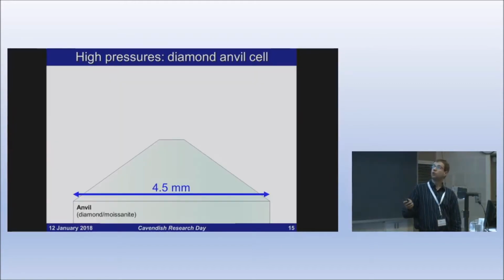And what we actually do in order to create the pressure and measure the sample is we work with the diamond anvil cell technique, where we use either diamond or, for lower pressures, moissanite anvils.